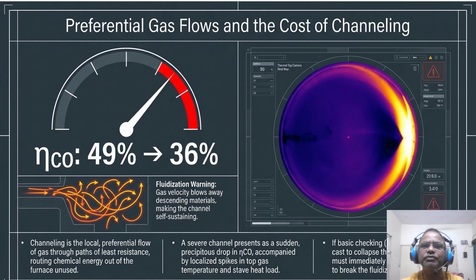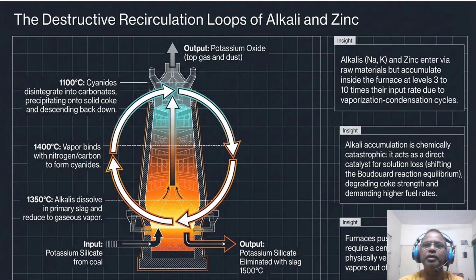So these physical disruptions are often magnified by the chemical recirculation of harmful elements like alkali and zinc, which were discussed in a much earlier presentation. So the destructive recirculation, we are going to see how the loop of alkali and zinc affects this. So this is the chemical silent killer. Alkali like potassium and zinc enter via raw material but accumulate at levels 3 to 10 times their input rate. Follow the white circular arrows at 1350 degrees centigrade.